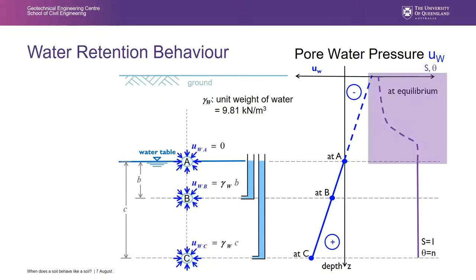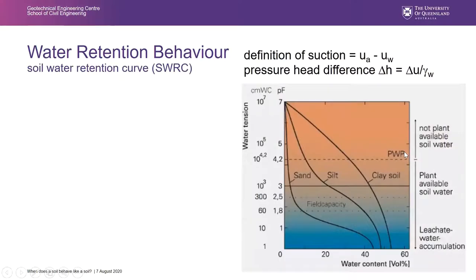pressure. And that is what we call the water retention behavior, which we need to know, for example, to be able to calculate water balance processes, not only within tailings, but also slopes, embankments, whatever the material is we are looking at. So at unsaturated conditions, we need to know this information and how we can get it. In geotechnical engineering, we took over a concept which comes rather from soil science, which is shown here. It is the water retention curve, which describes the water content, in this case the volumetric water content, versus the pressure head difference. And the pressure head difference is nothing else than the suction, as the difference in pressure between water and air phase, divided by the unit weight of water.